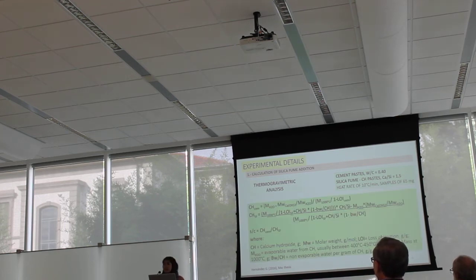In the experimental details, we calculate the silica fume content using thermogravimetric analysis on 7 pastes with water cement ratio of 0.4, with silica fume and calcium hydroxide pastes, because you have to know how much calcium hydroxide the silica fume is going to consume in a rich environment, but also how much calcium hydroxide your cement is going to produce. With this value you can calculate a silica cement ratio, and in a theoretical way determine the perfect addition of silica fume to consume all the calcium hydroxide in your cementitious matrix. This is the equation I use to calculate the calcium hydroxide contents and the silica cement ratio.